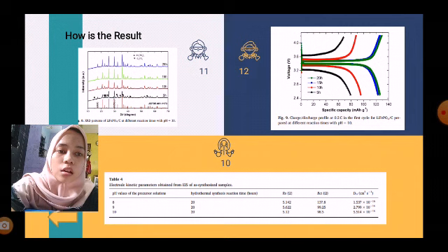The impurity phases Fe3(PO4)2 and Li3PO4 exist in the obtained lithium iron phosphate C when the reaction duration is 5 hours. As the reaction time reaches 10 hours or higher, only the pure lithium iron phosphate C phase is observed.